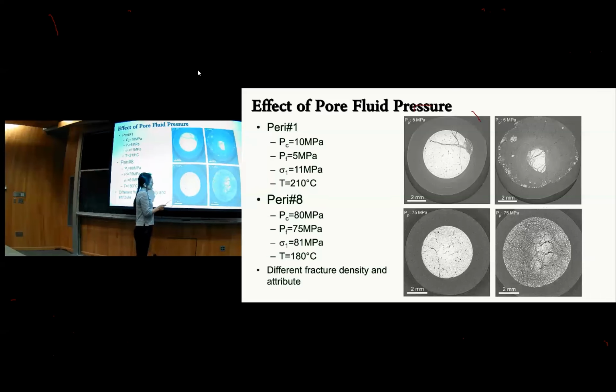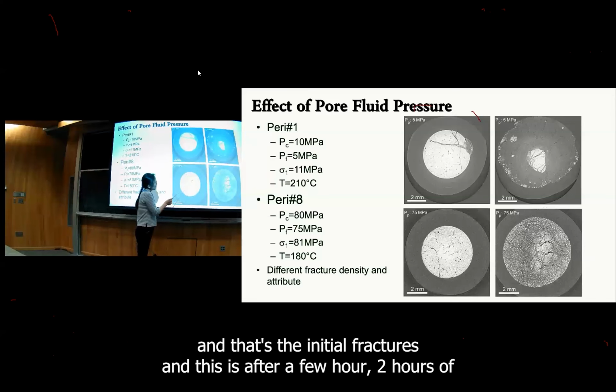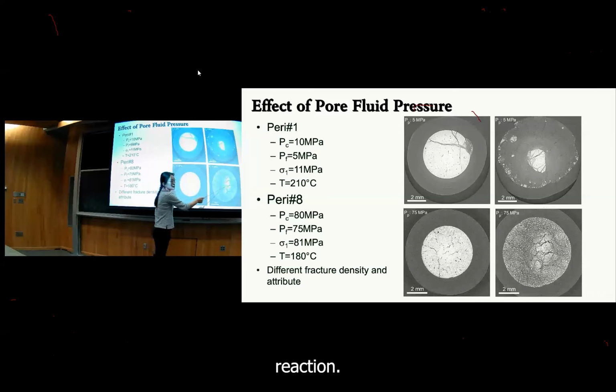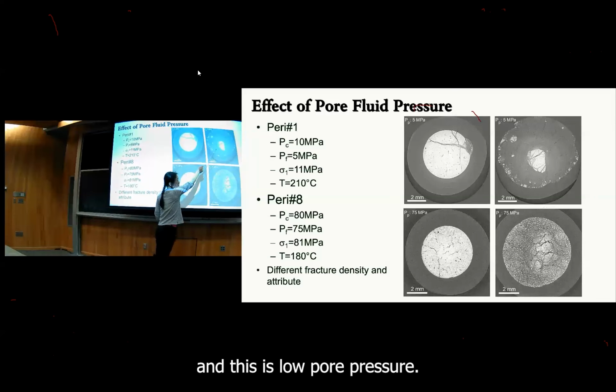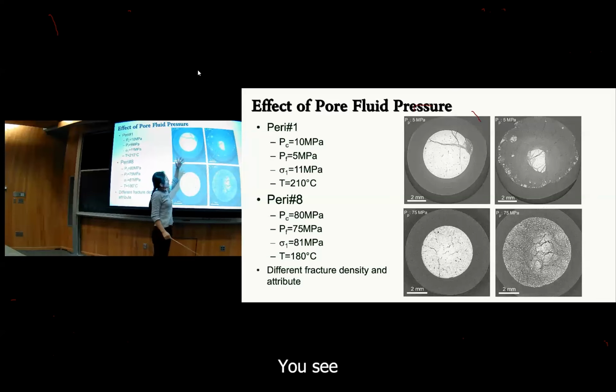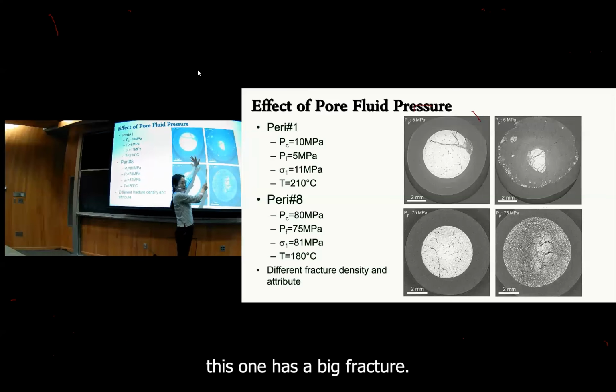However, what you see is this is our confining jacket. This is the periclase core, and that's the initial fractures. And this is after a few hours, 2 hours of reaction, right? Essentially, you break this down. And this is low pore pressure. This is high pore pressure. You see, this one has a big fracture.